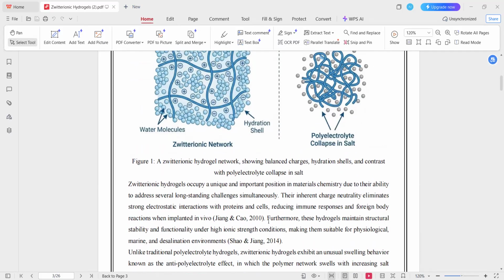Another unique feature of zwitterionic hydrogels is their anti-polyelectrolyte effect. Normally, polyelectrolyte hydrogels collapse in a salty environment, as you can see in the diagram, due to charge screening. However, zwitterionic hydrogels behave in exactly the opposite way. When the salt concentration increases, the added ions screen the internal electrostatic attractions in zwitterionic hydrogels, due to which polymer chains relax and become more flexible. That's why the hydrogel swells instead of collapsing. This unusual behavior is called the anti-polyelectrolyte effect and makes zwitterionic hydrogels very stable in physiological fluids like seawater and desalination environments.